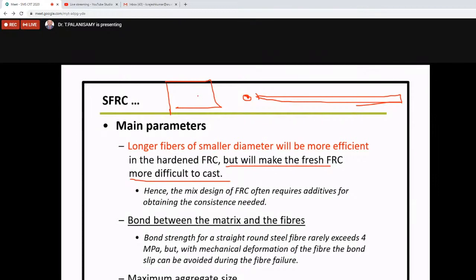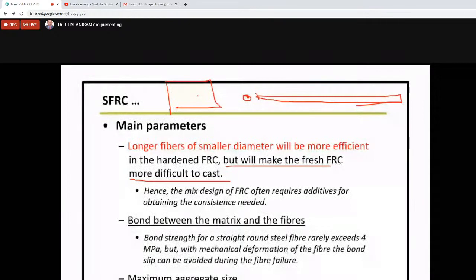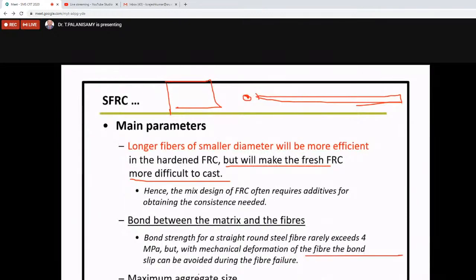Then bond between matrix and fibers. What are the other parameters we want to consider? Bond between matrix and fibers. The bond strength for straight round steel fibers rarely exceeds 4 MPa, but with mechanical deformation of the fiber, bond slip can be avoided during fiber failure. So the bond slipping mechanism is also a very important mechanism in fiber reinforced concrete.